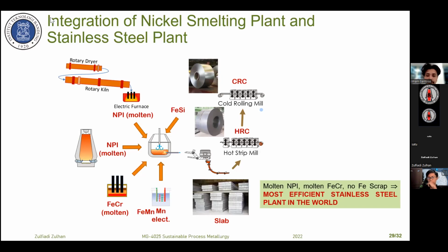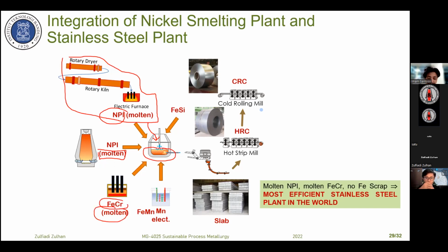As you have been informed before, the NPI or ferronickel is used as raw material for stainless steel making. Here's one route in Indonesia. The nickel pig iron in molten state is directly charged into the AOD converter. Maybe in some cases they mix with molten NPI from the blast furnace, with a nickel content of around 8%. It depends on the nickel content in the final products, and they also have ferrochromium in the molten state. But principally, we can also add ferrochromium directly in solid state, and the energy is enough to melt the ferrochromium in the AOD converter.